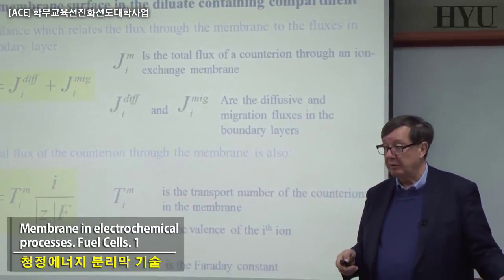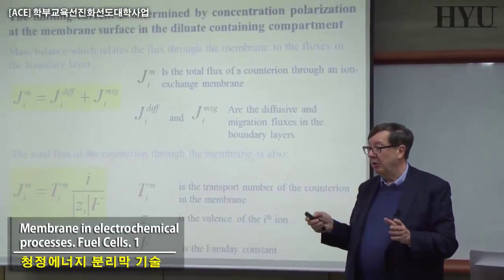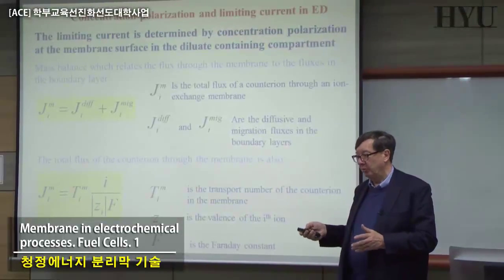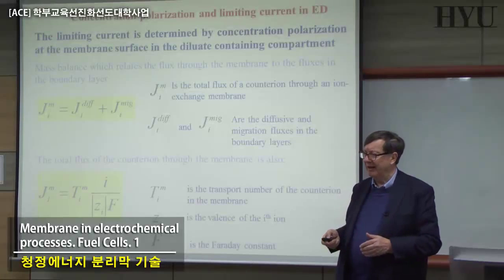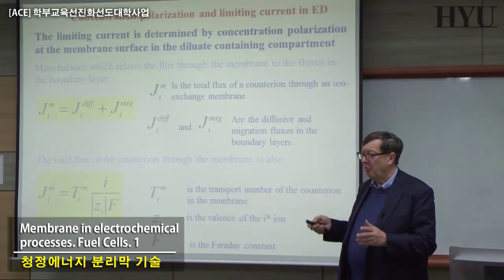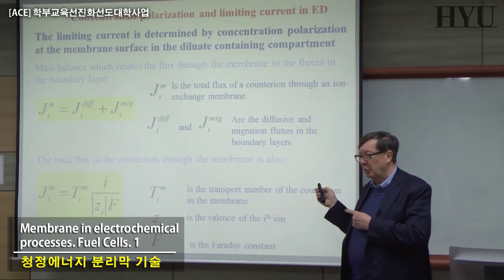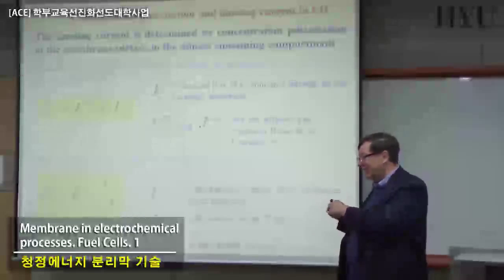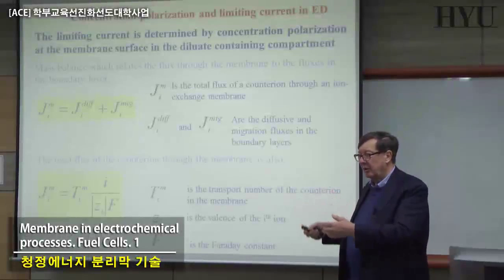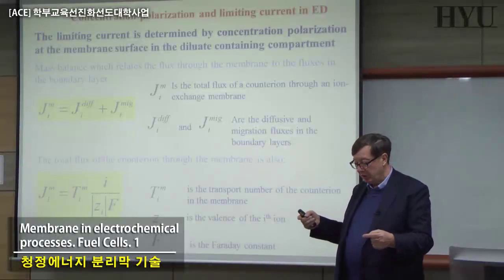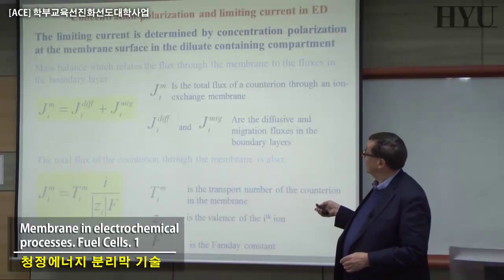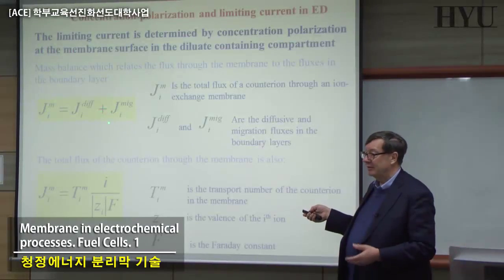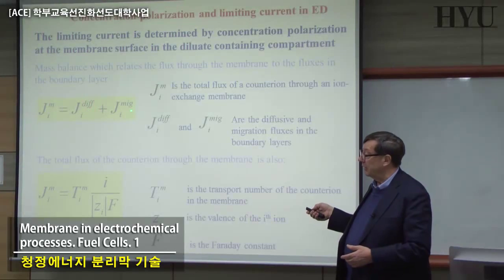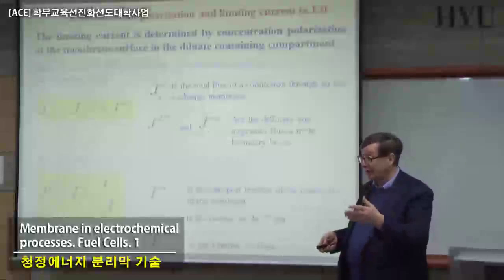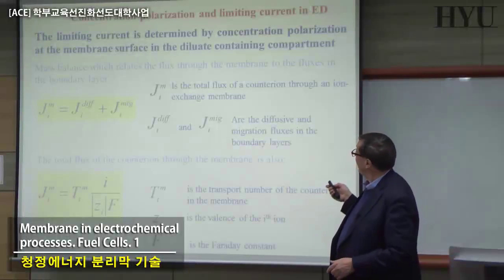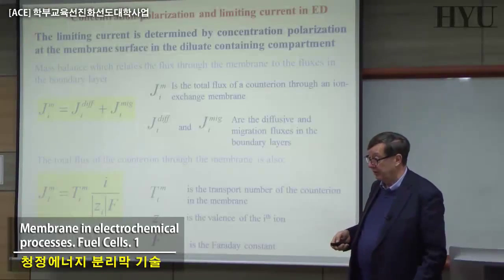Impedance spectroscopy, this kind of problem, years ago was basically very unknown. If you go to the famous book from Glasstone about electrochemistry, there was no mention of this kind of phenomenon, which takes place not just at the electrodes, but in the bulk. And that's why I was asking: with impedance spectroscopy, where you're working with alternating current, you can separate the effect, for example, of diffusion, migration, or formation of the double layer with time, etc. That's why it is interesting for characterizing and understanding phenomena of this kind.